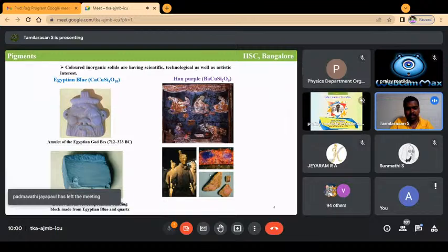And usually when we characterize colored materials, we use UV-visible absorption spectroscopy. We measure in reflectance mode and then convert to absorption mode using the Kubelka-Munk function. And then you could see there is an absorption band. Let me have my laser pointer, which I should have done far before. So it has absorption around the red region, leaving a window in the blue region. That gives rise to the blue color for the indium material. But for the gallium material, you could see the second absorption shifted a little bit. Also here, the first absorption shifted a little bit. It leaves a little window in the red region as well. So the combination of both red and blue gives rise to purple color.